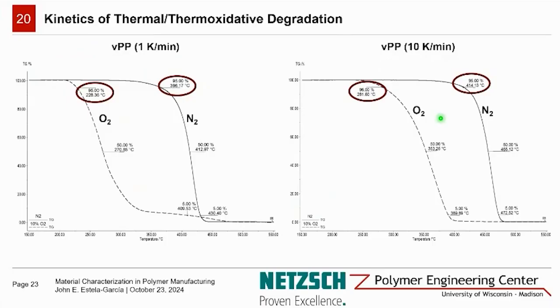We have three separate mass loss changes that are detailed: 5%, 50%, and 95%. These three steps are particularly useful, especially the 5% one, because it helps avoid issues where volatiles exuding from the polymer can be mistaken as polymer degradation. The presence of oxygen has a massive effect on thermal stability of the polymer. We can see that when we're comparing these slopes. It reduces the thermal stability of the material by up to 140 degrees in this case.